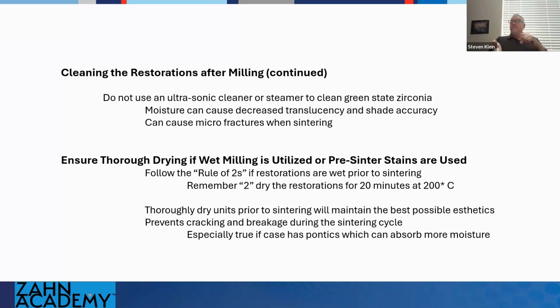So the same is true if you're using pre-sintering stains and characterizing the material that way. You would use what I call the rule of twos. So remember, you're going to dry the restoration for 20 minutes at 200 C, critical. And you want it to be as dry as possible, because not only will the aesthetics be affected, but you can risk cracking and breaking the restoration if you do not get it dry.